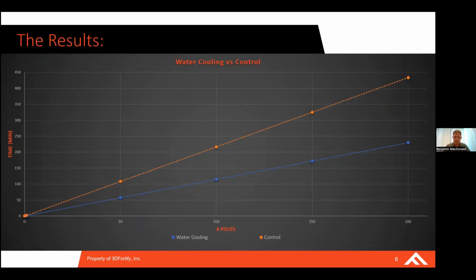The results. This is really the key thing that we found here. Running these two tools, water cooling versus control, we saw about a 50% reduction in time to mold 200 pieces. And that's something that's super important for a real world use case. If we look at any one of our partner CMs or ourselves internally, if we have to mold 200 parts, which is a pretty standard quantity of parts to mold for us, we're able to do 2 different geometries molded in a single day because we're able to mold 200 pieces in 4 hours. So if we look at our 8-hour workday, that's 2 mold tools we're able to process in a single day, effectively doubling our capacity to mold parts.